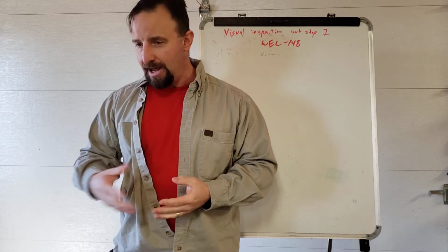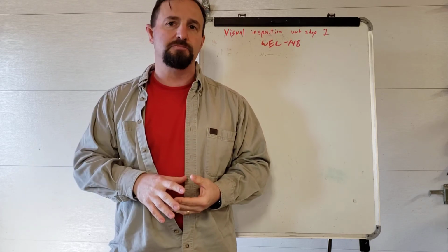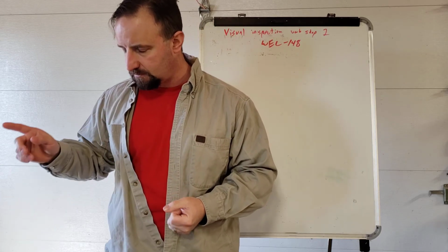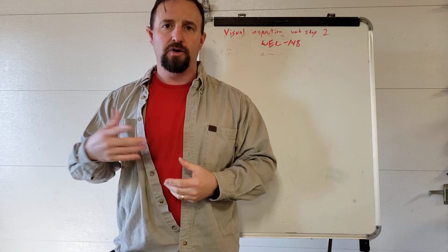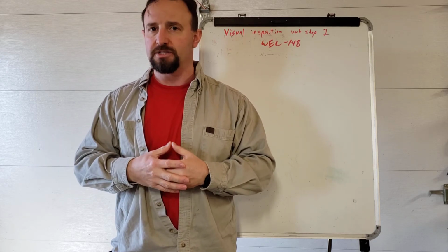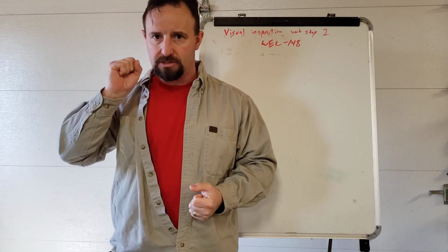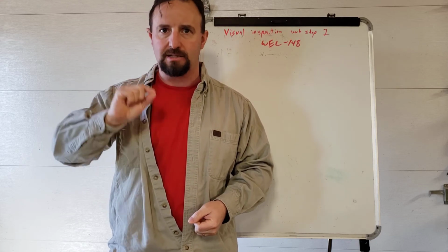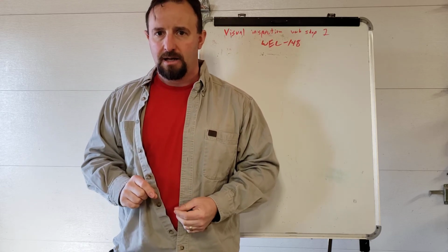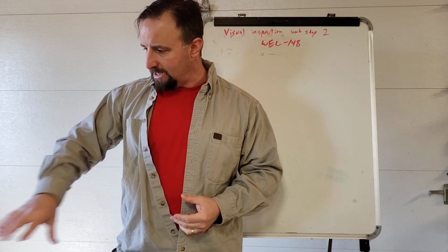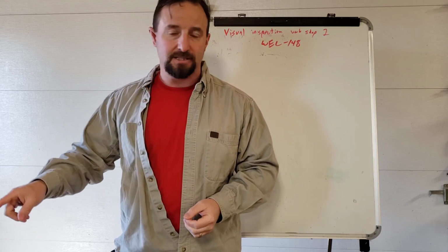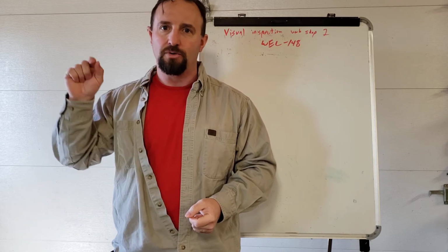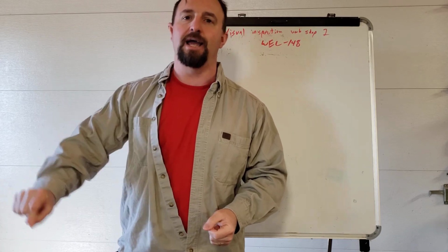You can increase the exposure time with an x-ray for this sort of thing, and we can increase our exposure time to the point where the weld just completely disappears. Those little pieces of tungsten that are in there will stand out just like little pinpricks, little stars in the sky. And so, like I said, I like pulling this one up because it's in our textbook. It's in every textbook I've ever seen, and it's labeled wrong every single time.